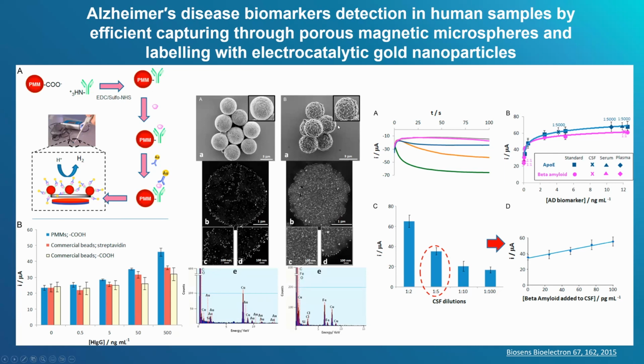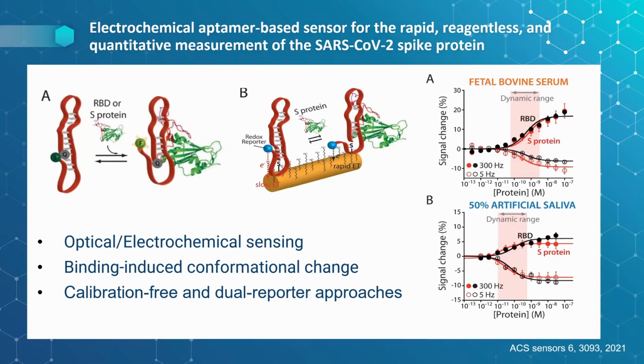You see the images of the particles we use as support for the antibodies, and then those that are now decorated with gold nanoparticles during the sandwich formation, and more data that show the correlation of the results, and of course microscopic images and evidence of the presence of these particles. And some data showing the response of the sensors toward increasing concentration of this biomarker for different kinds of biomarkers.